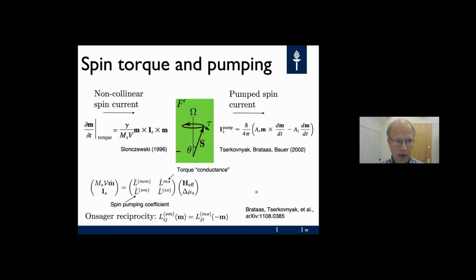As I already mentioned, there are two phenomena which are reciprocals of each other. A spin current that is non-collinear to the magnetization direction drives a torque, which drives the magnetization precession. And the magnetization precession itself pumps spin current into an adjacent metal, and this pumped spin current also acts as a damping of the magnetization precession.